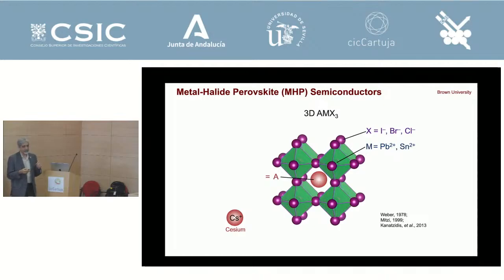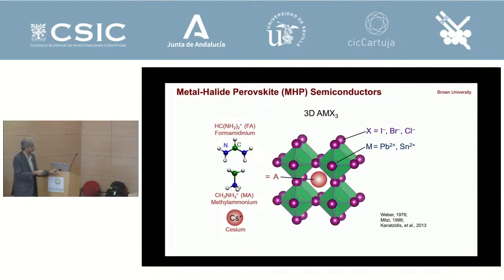And therefore, cesium barely makes it. Francium, of course, will make it, but it's radioactive, so you don't want to use that. And so therefore, you have to actually use molecules, cationic molecules, in order to stabilize the structure. And one of the popular ones is methylammonium, and the other one is formamidinium. So for ceramics people, it's very fascinating that you have an organic molecule that's actually rotating. And when it sits there, it doesn't stay like an atom. It spins, right? And you have a crystal. So it's very different for ceramics people to think about these structures. And that took me a while as well.